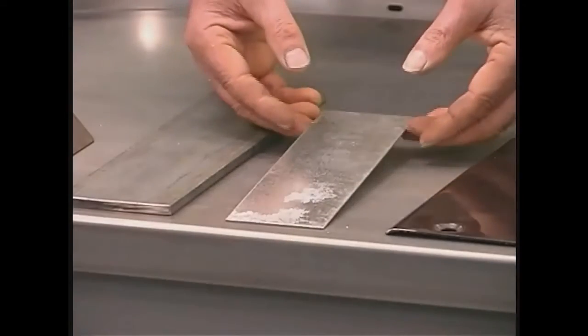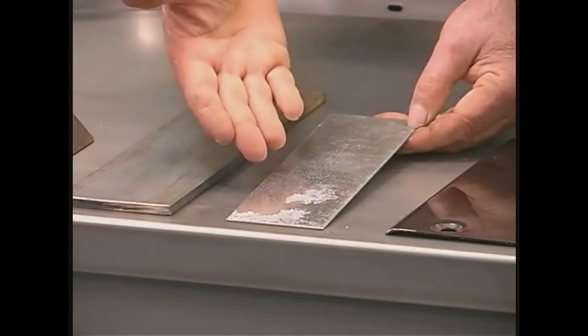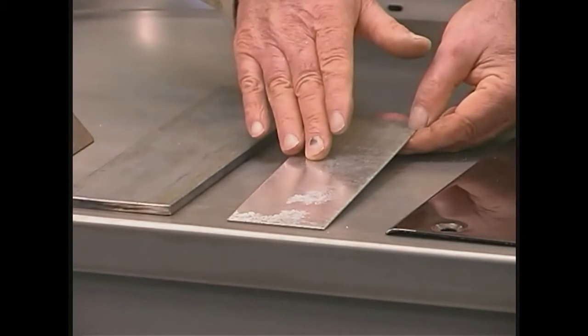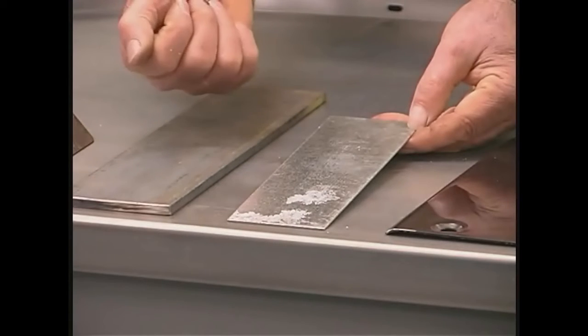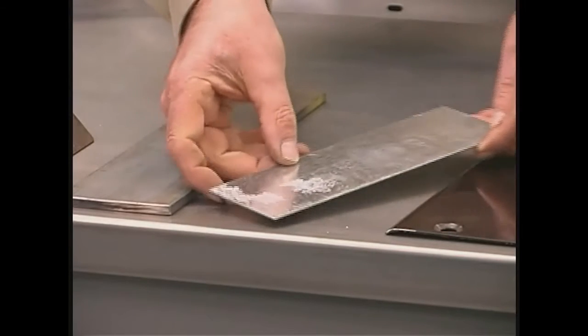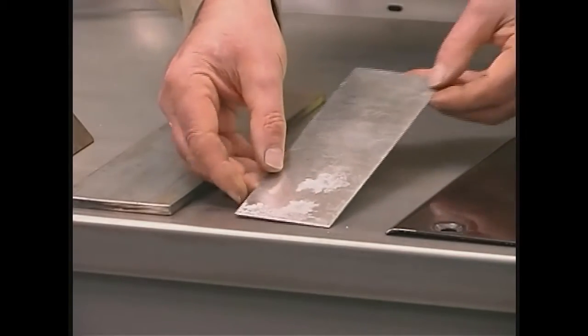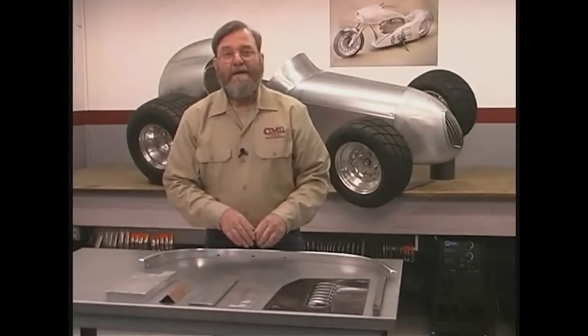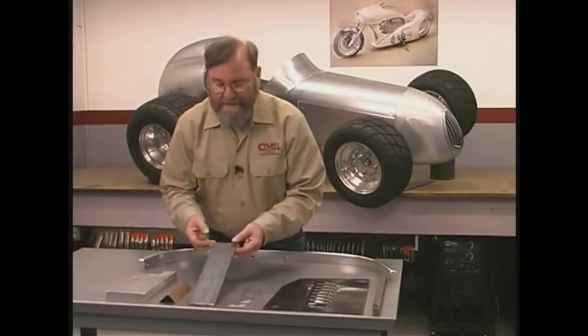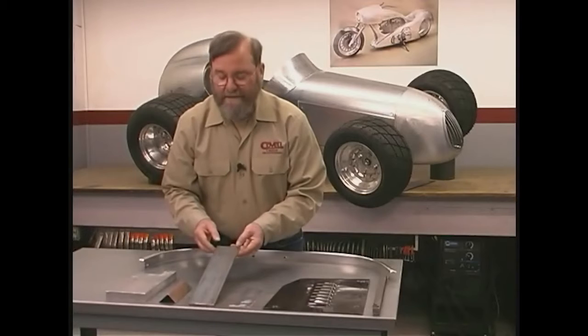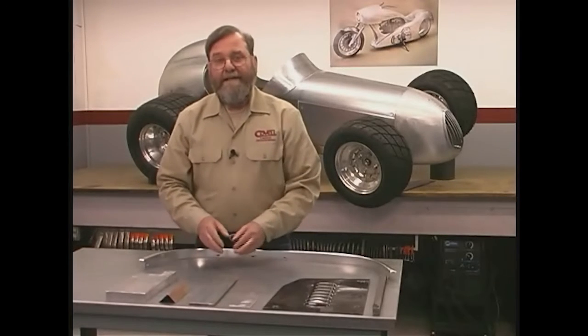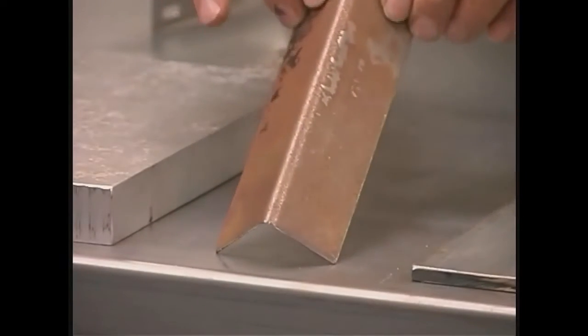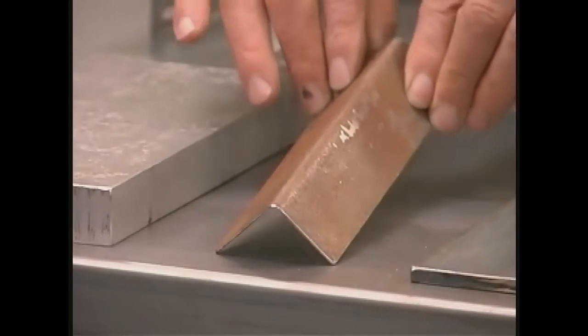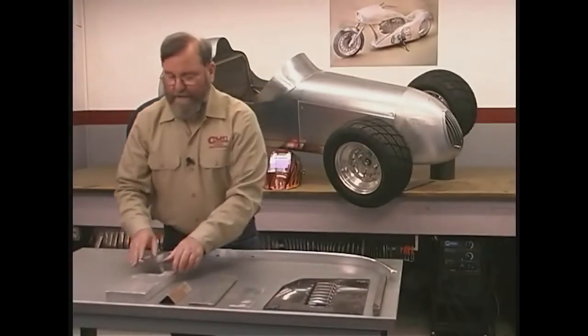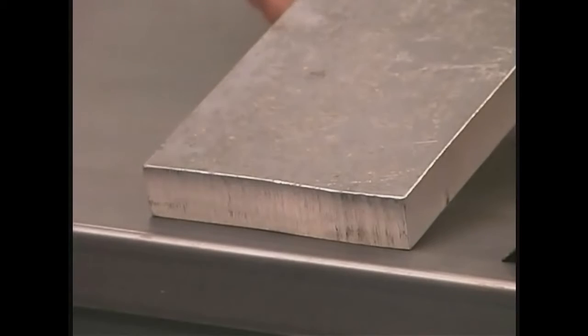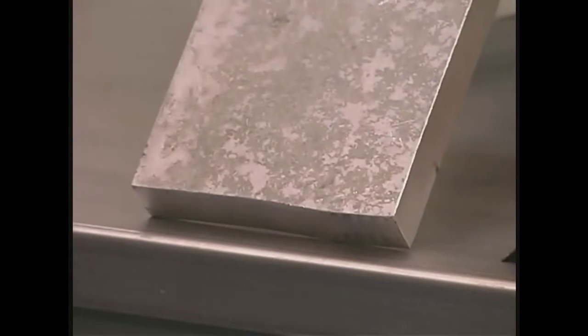Anything that's galvanized needs to be stripped down to bare metal. What makes galvanized metal galvanized is a coating of zinc on the surface. When zinc is heated, it gives off a fume that's poisonous. So it's very important to strip any galvanized material before heating or before welding. Hot rolled steel has a scale on the surface, and that scale has to be stripped before it can be welded. Any metal with rust on it needs to be cleaned. You can't make a good weld through rust. Any corrosion on the surface of metal will prevent the puddle from flowing well, so it's very important to clean off corrosion.